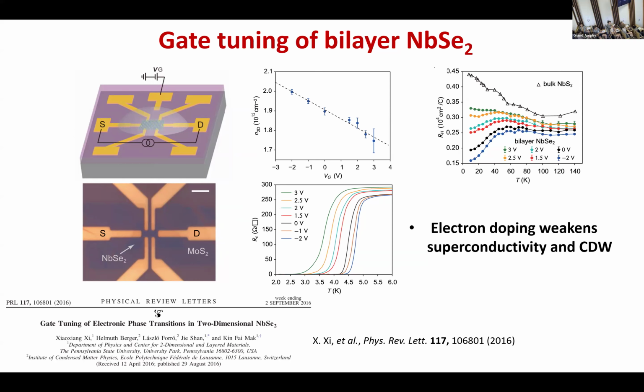However, I think just from the tunability here, this is very high. This is 3 times 10 to the power of 14. For this tunability, you would think that without the capping, without molybdenum disulfide, you could have this. So seeing this large tunability actually tells you that it could be some kind of chemical process. Exactly what the process could be is that hydrogen atoms, protons, could get injected into the sample and donate electrons into the system, because protons are so small that they can go through molybdenum disulfide. This is just my speculation, not really proven.